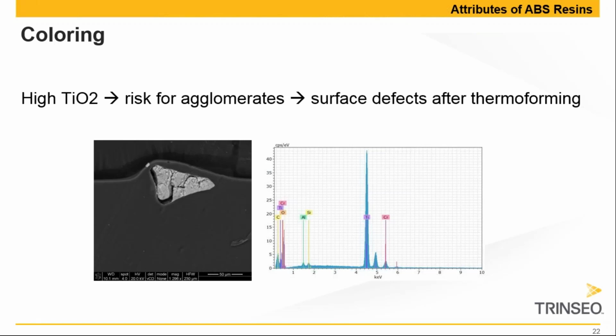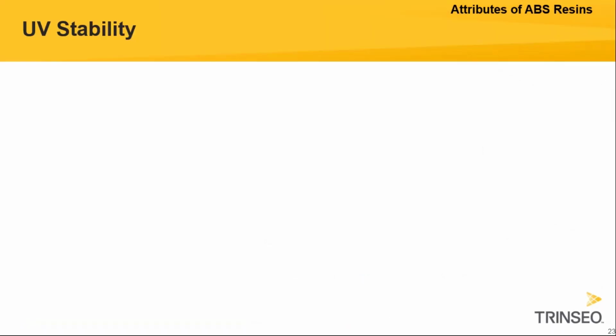And when we analyze this inclusion with elemental analysis, which you see on the graph on the right side, you see a major peak of titanium. And you see in the middle, and you see on the left side, there is oxygen. So clearly you can say this is very likely titanium dioxide agglomerate due to the too high usage of pigment dosing. Now we move into another attribute for the ABS. We move into UV stability.